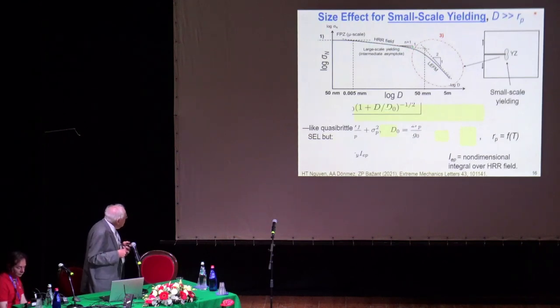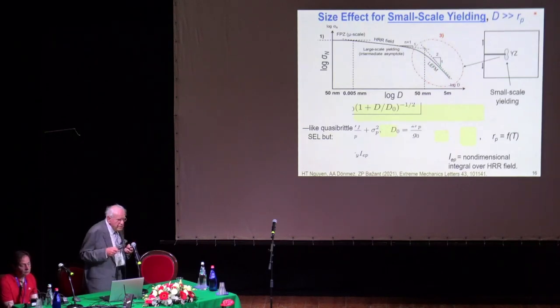Same picture again, but there's a formula which you don't see. As you can see, it is the same as the size effect formula which I showed, same as for concrete, except the parameters are defined differently. They depend on the yield stress and the radius of the yielding zone, and you can identify from size effect the fracture energy. This gives the transition from the first asymptote to the last one, jumping through this asymptote, again satisfying all the asymptotic properties, and it gives results which are identical with the J integral within admissible error.